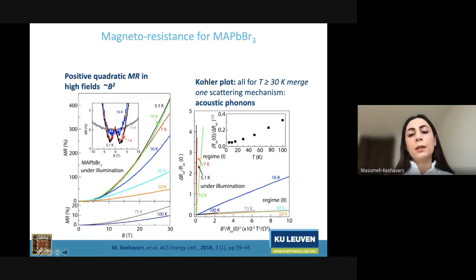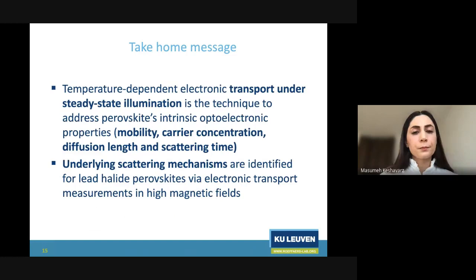And if we plot the square root of the magnetoresistance as a function of temperature, this is related to the inverse scattering rate of the carriers. If it scales with temperature linearly, it is an indication of acoustic phonon scattering being the dominant scattering mechanism. And here we approve our measurements, the first one, independently.